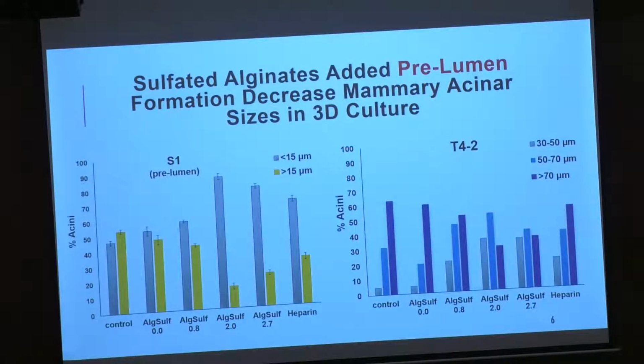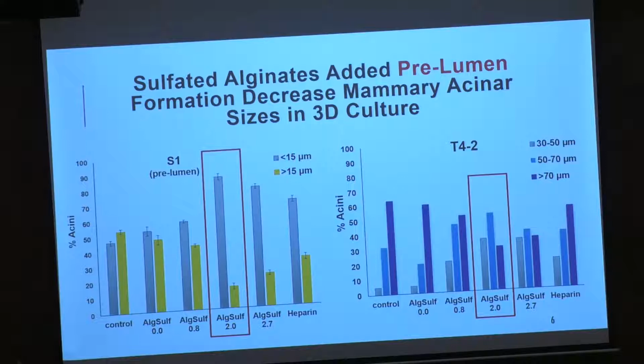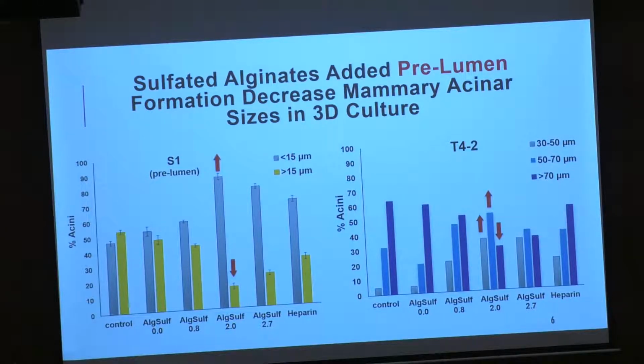Then we moved to the 3D model, where we added the alginates early in culture, which means we are adding these alginates pre-lumen formation, compared to the S1 cells. And again, alginate sulfate 2.0 had the most potent effect, as it decreased the diameter of the acini that we had. The frequency of small acini increased while that of the large acini decreased. And the effect, again, was more potent in the T4 cells, as those of sizes 30 to 50 micron increased dramatically compared to their normal.